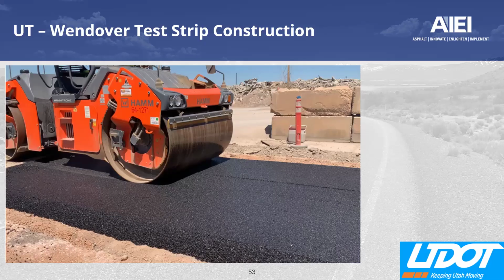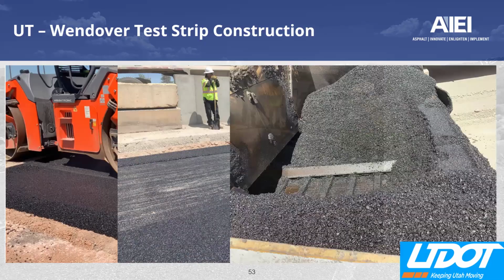Yeah, thank you, Johnny. The only thing I will add is certainly the Utah experience. First of all, with all polymer modified materials, especially when you start getting higher polymer loadings, recognize that increased binder temperature, especially in storage, can be very counterproductive. You can increase the cross-linking rate and therefore increase the viscosity as it sits in the tank. I call it viscosity creep. And so you want to be careful to work with the supplier and the polymer supplier in particular to make sure that you are not exceeding their recommendations of that temperature to avoid that scenario from occurring.